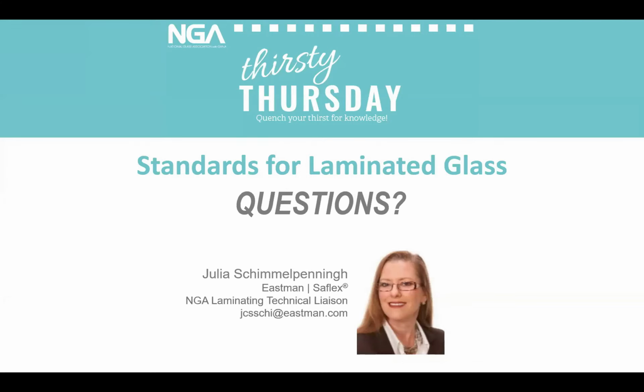If you're looking at using an edge seal for moisture or salts and things like that to keep it out, and you're not butt glazing it or you're not doing anything like that, there are some products that are available that can do that very, very well. If you're looking at butt sealing that, then I have to refer you back to the sealant manufacturers and what we'll call edge seal suppliers to make sure that they have the proper data that says, yes, this is going to stick to glass for the proper amount of time and at the proper levels to give you the adhesion and durability you need to keep your unit sealed up. Because the interaction with the inner layer is only one small part of selecting the proper seals and edge seals or sealants. So you have to look at all of the rationale for doing that.